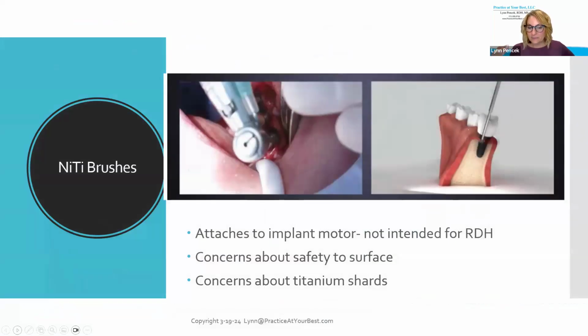These are nickel titanium brushes. These brushes you can attach onto the implant motor. So I'm thinking these are really geared towards the periodontist to work with, not necessarily the hygienist. I have concerns with these titanium brushes because we talked about metallosis and how the corrosion layer can come off easily. If I'm working with a brush being spun around very fast, I'm going to create these titanium particles. And so I'm concerned about shards being released.